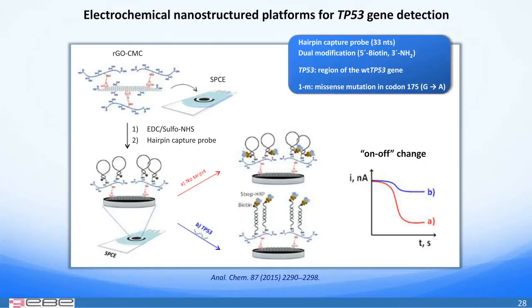By using a streptavidin-peroxidase conjugate as an electrochemical indicator, the hybridization was monitored by recording the amperometric response measured upon the addition of 3,3',5,5'-tetramethylbenzidine, or TMB, as a redox mediator and hydrogen peroxide as an enzyme substrate, leading to a typical on-off change as a consequence of the remarkably increased distance between the attached enzymatic conjugate and the electrode surface, which hinders the electron transfer. The synthetic target sequence used corresponds with a region of the wild-type gene and the single-mismatch sequence with a mutant genotype that contains a single nucleotide change at codon 175, leading to cancer by triggering the inactivation of this tumor suppressor protein.